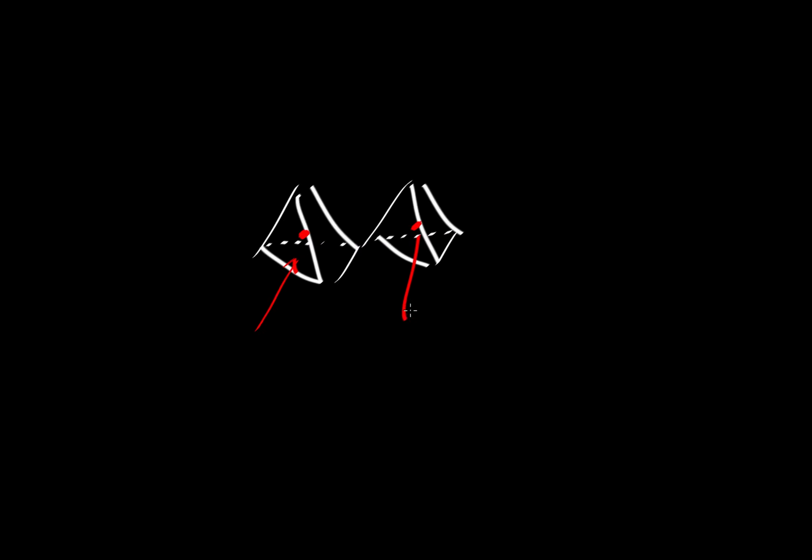Let's get rid of all this writing. If we have a tetrahedron here, and we have another corner-sharing tetrahedron here, here's the back edge of it, and we have some cations that occupy the center of these. So there's an atom here and an atom here. If these atoms are especially high in charge, let's say you have a phosphorus atom with a 5+ charge, then it's unlikely that you would even have corner sharing, and so this would be an unstable arrangement.